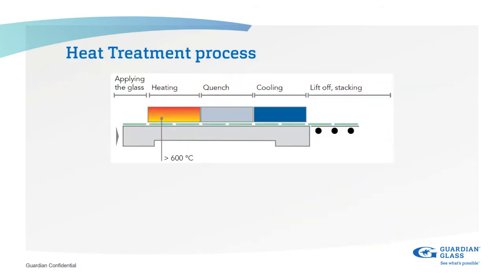The heat treatment process. So what we have here is a side view of a typical heat treatment tempering furnace or heat strengthening furnace. As you can see, the area that's highlighted yellow and red, that's the furnace. Usually this has a temperature of over 600 degrees centigrade, around 650, I should say.